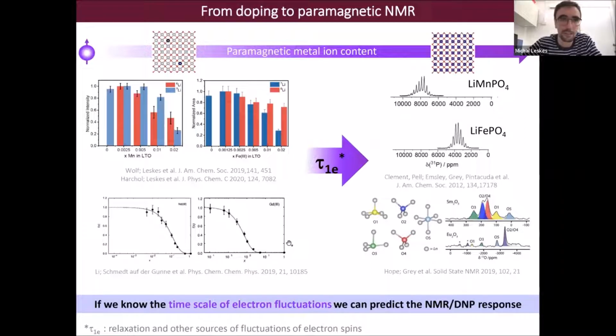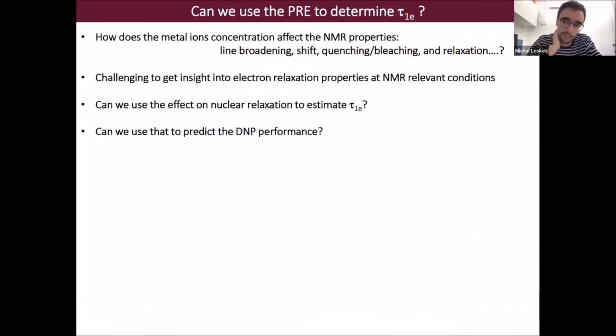In principle, we could measure electron relaxation times with EPR. However, this can be very challenging, especially in the conditions that we are interested in for NMR, like 100 Kelvin or above and high magnetic fields. So we asked ourselves if we are able to determine this parameter just from the paramagnetic relaxation enhancement itself. And if we can, can we use this parameter, tau1e or T1e, to understand and rationalize the NMR response that we obtain, and eventually even predict DNP enhancements? I'm going to try to answer this question in the next few slides.